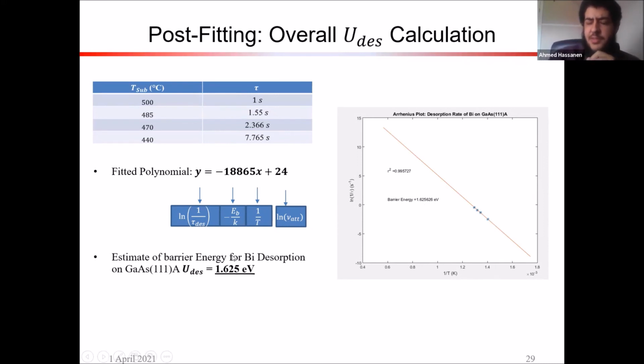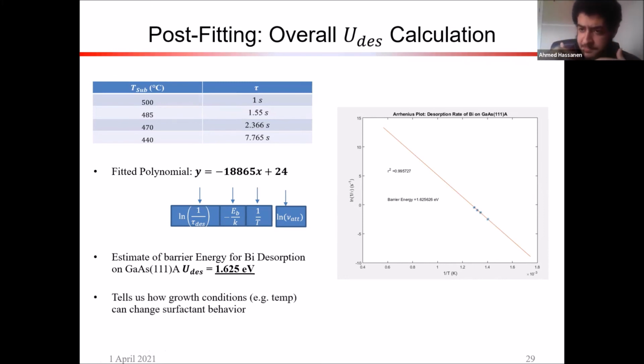Now, this is the first time that I think the desorption barrier energy has been calculated for bismuth on gallium arsenide 111A. And gallium arsenide 111A is basically the gallium terminated version of gallium arsenide 111. And so this tells us how the growth conditions, for example the temperature, can really change the surfactant behavior.